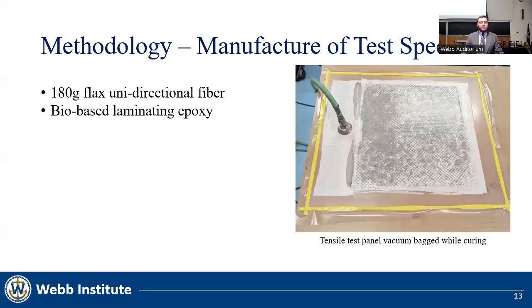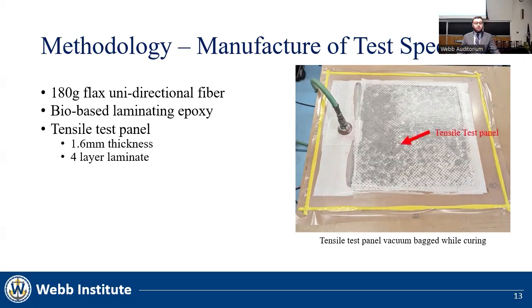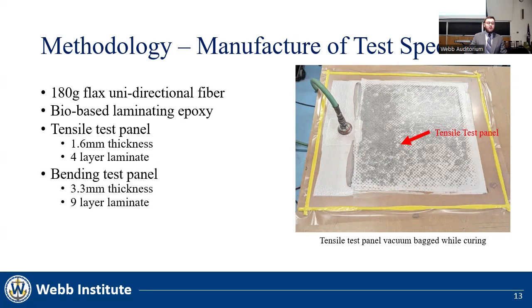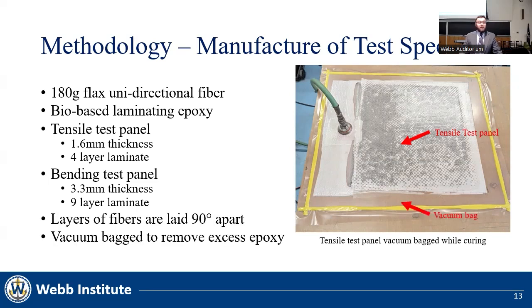To manufacture the test specimens, I used 180-gram flax unidirectional fiber and a bio-based laminating epoxy. This is the tensile test panel with a 4-layer laminate resulting in 1.6 millimeter thickness. I also constructed a bending test panel with a 9-layer laminate and a 3.3 millimeter thickness. The layers of fibers are laid 90 degrees apart for each layer, and then vacuum bagged to remove the excess epoxy and air from the composite during the curing.